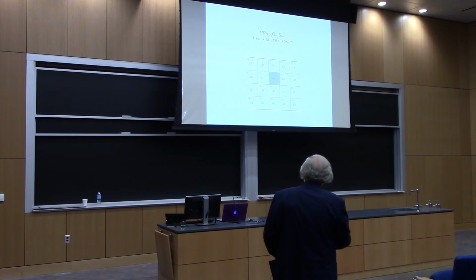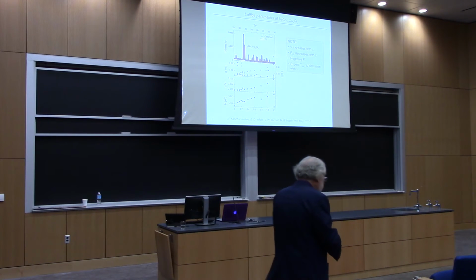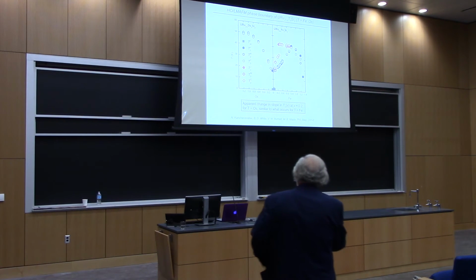So let me just mention the osmium work. This is something we don't understand very well, but it's very interesting. And so here now we're substituting osmium. And so here you can see that the a and c parameters, the volume, increases. And so this would be like negative pressure, so you think that all the trends ought to go the other way. They don't. And so here is the phase boundary you find, so osmium substitution goes this way. And here's the phase boundary.